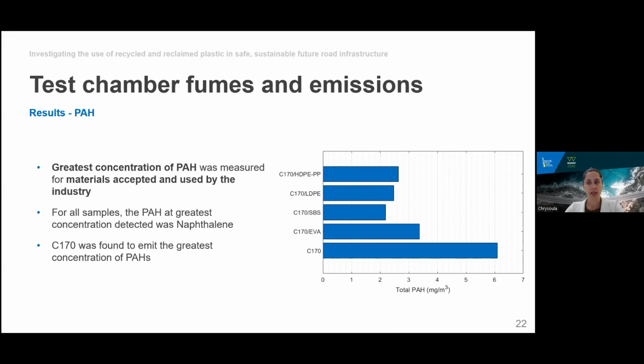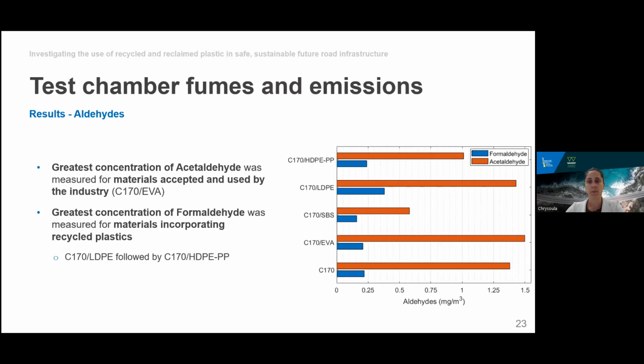C170 and EVA modified C170 were also found to emit the greatest concentration of PAHs, with those measured for C170 being almost double in concentration. We also noted that irrespective of the binder, the PAH most detected was naphthalene. For aldehydes, we detected formaldehydes and acetaldehydes. The greatest concentration of acetaldehydes detected was from the commonly used EVA modified C170, while LDPE modified C170 was found to emit the greatest concentration of formaldehydes.